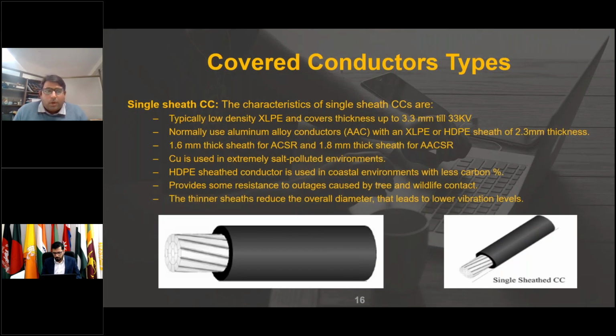So covered conductor type 1 is the single sheath covered conductor. The characteristics of these single sheath covered conductors are that they are typically of low-density XLPE with cover thickness up to 3.3 millimeter till 33 kV. Just to add to this, the insulation has a direct link with the voltage. As you increase the voltage level, the insulation gets thicker and thicker. So normal use of aluminum alloy conductor and XLPE or HDPE sheets of 2.3 millimeter thickness can also be used. So 1.6 millimeter thick sheet for ACSR and 1.8 millimeter thick sheet for AACSR. These are basically the classifications of the thickness of the insulation that are attributed to those conductors when they are in covered conductor arrangement, single sheath.